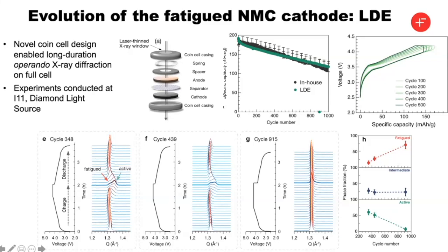And so this is a comparison between our in-house coin cells versus these long duration experiments, and we're getting very good electrochemistry, or at least very similar electrochemistry. And then this allows us to interrogate what's going on after multiple cycles. And so what we do is we come back sporadically once a month and we collect the diffraction pattern on charge and discharge to follow what's going on.